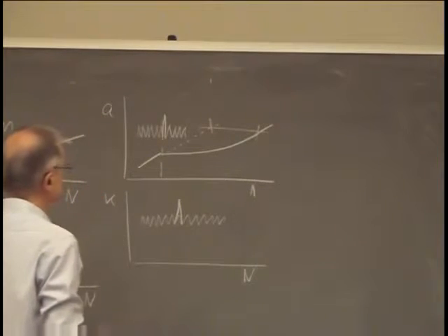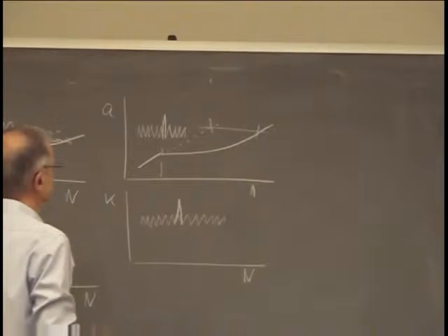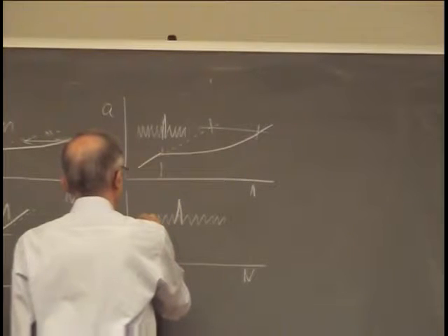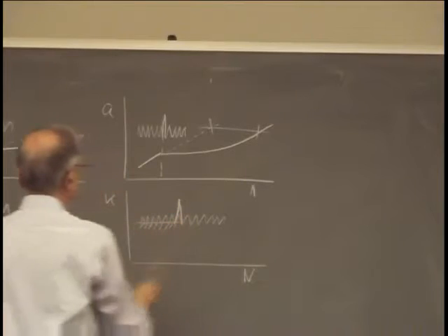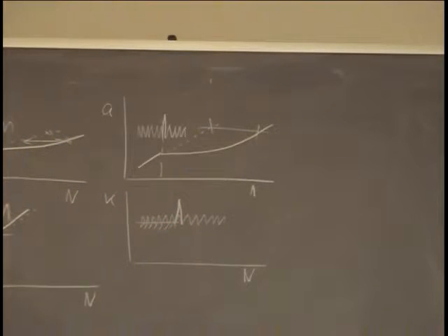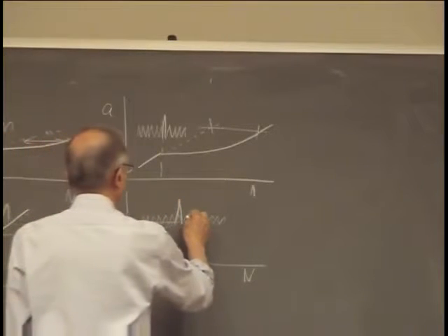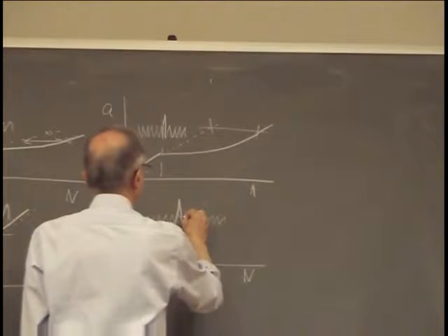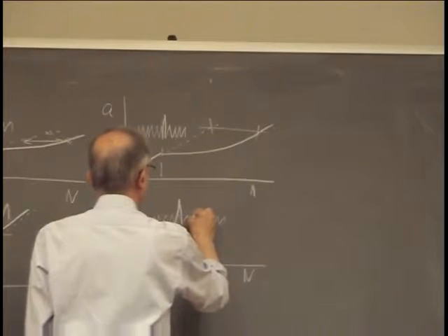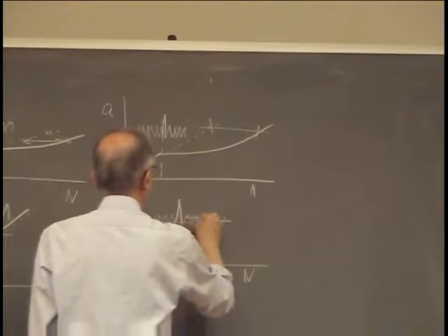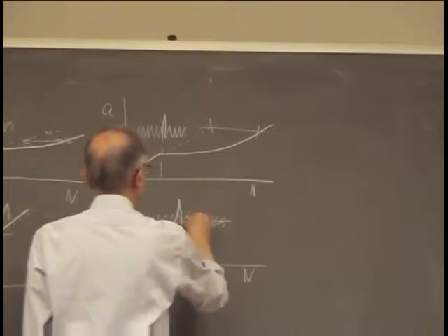And we know that crack closure happens. Maybe the crack is closed here. And we have a certain delta K effective, which is above the crack closure level. And when we apply the single peak overload, all of a sudden the crack closure is much higher, and crack closure decays with time to the previous equilibrium condition.